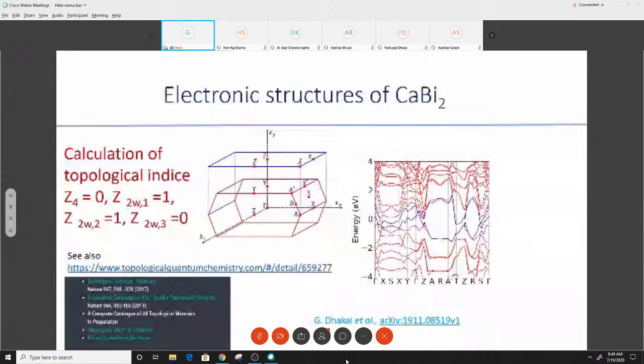And this is the website we normally look at to see whether some materials are topological or non-topological. It's highly recommended to check it. The other thing is, in this one we check the symmetry indicators, and here Z4 shows 0. That indicates it's not a strong TI. And there are two indicators, and they are not 0. That means it's a weak TI.